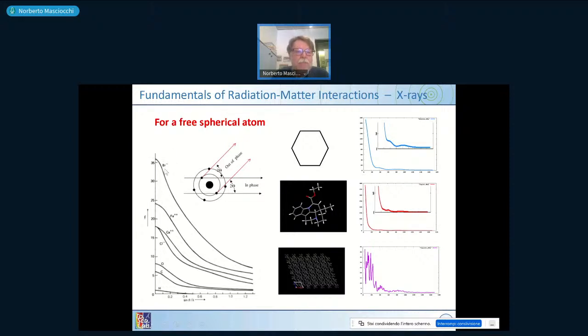As you can see here, bromine minus, iron 2 plus, calcium 2 plus. These are elements or ions with different quantity of electrons, and these scale up with electrons. Because intensity goes with the square of this factor, you can see that 1 times 1 of hydrogen compares, for example, to bromine, which is 35 by 35, which is about 1000. That means the scattering of hydrogen is nearly negligible in the presence of heavy atoms. That's why it's normally said that hydrogen atoms cannot be easily seen by X-rays.